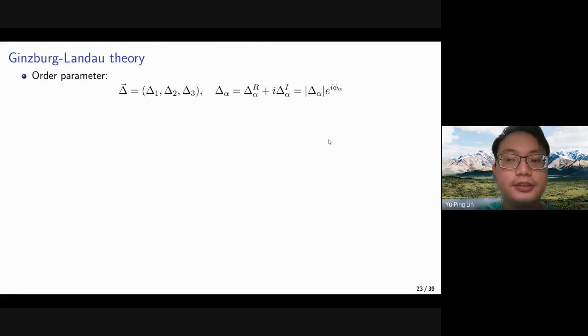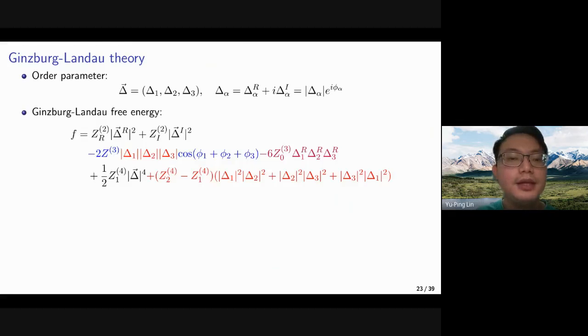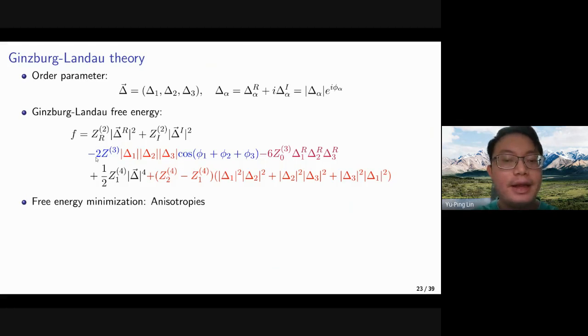So the next thing to do is to analyze the interplay between them. So we look at the order parameter at the 3 momenta, 1, 2, 3. Because we're combining the real and the imaginary orders, we could define it as a magnitude and the complex phase. So we could derive a Ginzburg-Landau free energy, where we have quadratic order, quartic order, and the cubic order. By looking at the quadratic, if the quadratic order turns negative, there could be the development of the order parameter, which corresponds to the formation of charge density waves.